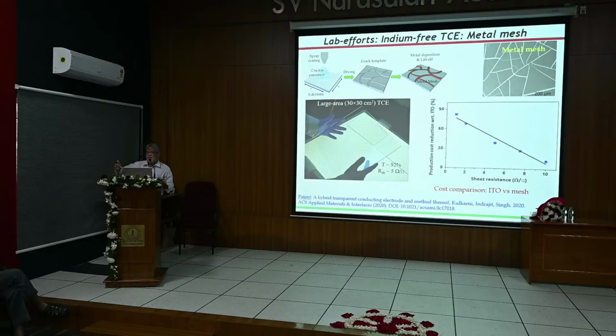If you make them around 500, 800 nanometer, less than a micron, they already fall into that kind of category, less than 1 ohm per square. So you can see data points here, very low sheet resistance. The Y-axis actually talks about the commercial aspect, the production cost compared to the standard ITO. You can readily see that if you're talking about ordinary sheet resistances on glass, ITO coating would do. Cost-wise, it may not make much difference. But if you want to go down in terms of sheet resistance, this is where the distinction comes up.